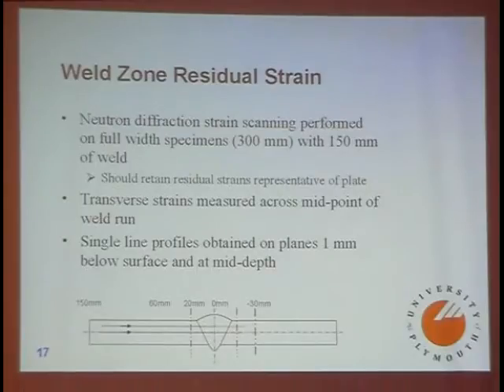Right, so now I've got the microhardness data more or less sorted out. Now I need to get the residual strain data sorted out. So we did neutron diffraction strain scanning on full width specimens containing 150 millimeters of weld run, on the assumption they should be representative, and we've measured transverse strains across the midpoint of the weld. And again, we've measured along the same sorts of lines, obviously not to scale, but it's indicative. We've measured a matrix of points from minus 30 millimeters up to about plus 60.